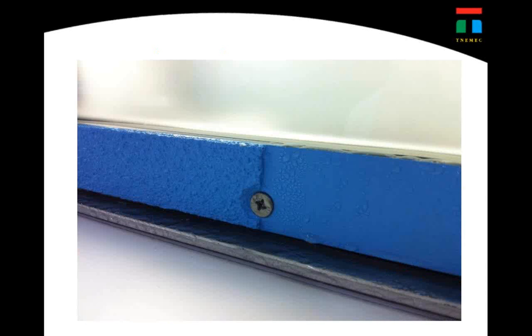So what you're looking at is very typical of what I believe is a kind of revolutionary approach to solving a lot of sweating and condensation issues, especially in thermal bridging applications: a virtual elimination of condensation through this technology. Now, if you can imagine, that window frame is at 42 degrees, and the inside temperature is what's causing it to sweat. So if I put on Aerolon at that thickness, and I'm slowing the migration of temperature to the point where it never reaches dew point, that is the benefit behind this approach. So this is why we think we have a pretty significant avenue to pursue with how to reduce condensation effect, especially in cavity wall construction where, obviously, we do get that occurring presently.